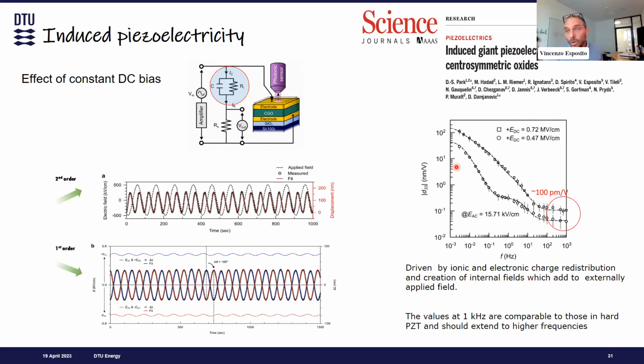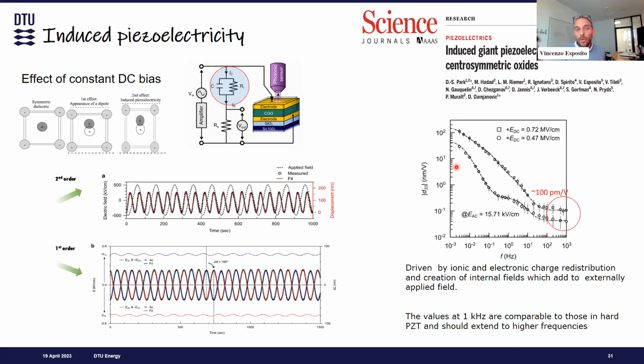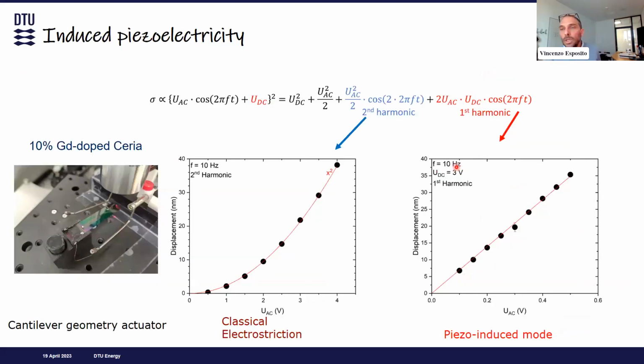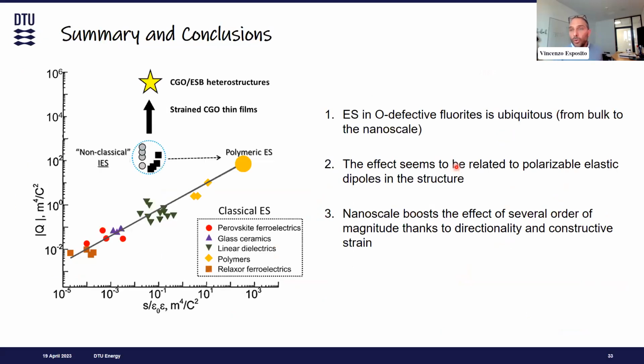This is nothing new. It is known that if you have a DC field on a centrosymmetric system, you can get a linear response. This has already been formalized. But what is nice to see is that we can actually apply this effect, and it is pretty large, especially at low frequency. So with this, I conclude the part that oxygen-defective metal oxides have electromechanical properties that are ubiquitous. We find them in polycrystalline, in single crystal, in columnar structures, and basically at any scale. And the nice part is that there is still room for manipulation and improvement. And we hope to see these materials in action in real life very soon.